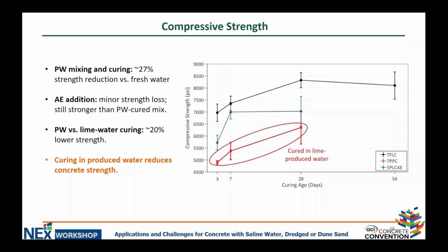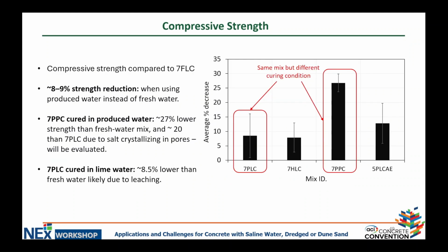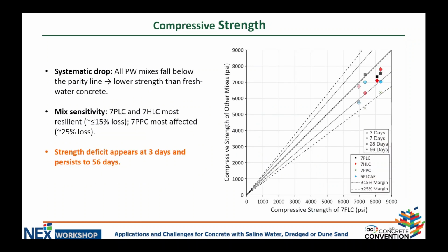That was, as I said, the one made and cured in produced water. So as we can see, this figure just shows the percent decrease in compressive strength of these different mixes compared to the reference mix, the fresh water mix. And these two mixes are identical. One of them has only an 8% decrease, cured in lime water. The other one, cured in produced water, has a 27% decrease. So that is basically the main thing we can see from here.